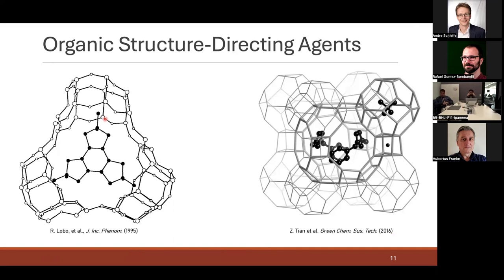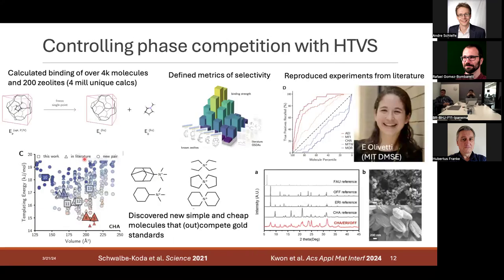So folks were typically worried about binding, but they weren't worried about selectivity, right? It's not just that this molecule fits in this pore, but there's another 249 materials that could come out. We probably need to test how this molecule behaves against those materials too, and not just against the material that you want. So that's exactly what we set out to do, right?